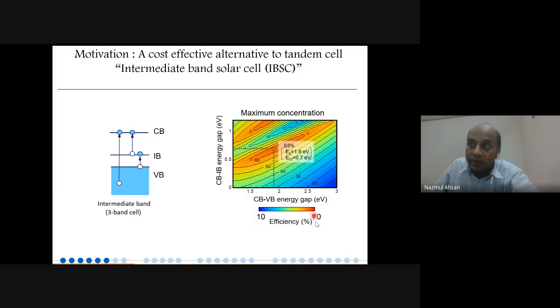Red means 70%, close to 70%. And this color tells you that if you have a piece of semiconductor whose band gap is close to 1.9 electron volt, and the intermediate band is close to 0.7 electron volt, and if you can make this kind of semiconductor, then you are pretty close to having a solar cell of 63% theoretical limit. And this is good news, because more than 60% you can convert to electricity, okay?